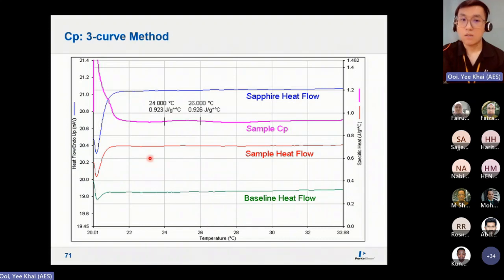It's something like this. This is the curve from the Sapphire standard, this is from the sample, and this is just the baseline, meaning empty pan only. When you put all three curves into the specific heat calculation software, it gives you the Cp curve for the sample. Now we can mark the temperature we want together with the specific capacity.